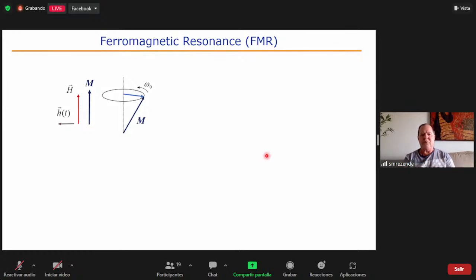How can we see this experimentally? We have a ferromagnetic material. This can also be done in ferrimagnetic materials and also in antiferromagnetic materials. We apply a magnetic field and we apply a driving field, microwave, for example. In antiferromagnets, people are using terahertz radiation, very high frequency. And then the magnetization will precess, and this can be done by placing a ferromagnetic sample inside a microwave cavity or a microwave device that we place between the poles of a magnet. That's a microwave generator. The microwave comes here, and we observe the reflection.